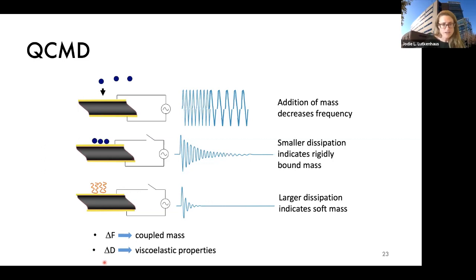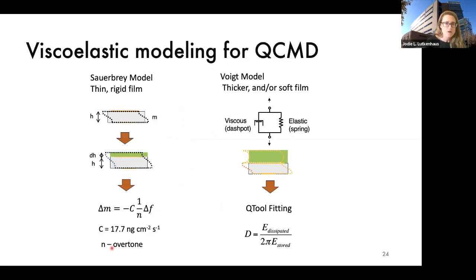So the raw data will consist of changes in frequency and dissipation. We can do viscoelastic modeling. If your film's really rigid, we can use the Sauerbrey model. That is almost never appropriate for a polymer electrode. Most often you end up having to use a Voigt model or even a modified Voigt model to account for the viscous component, because of that viscous response.